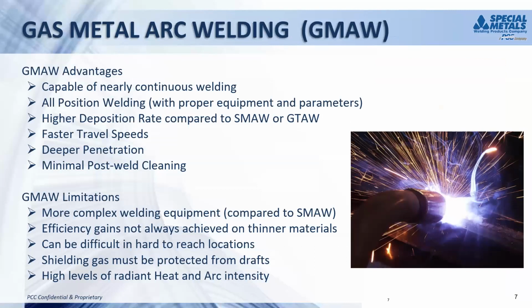All right, now we'll skip over to some gas metal arc welding, or MIG welding. This is probably gaining a lot of steam in the last few years with the nickel alloys because you can do much more continuous welding. We're now starting to put wire in drums, so you can do, not thousands of pounds, but at least 200 to 500 pounds without having to change a spool of continuous welding. Obviously that gives you faster travel speeds and much higher deposition rates, so you can put more metal down. Even with the proper equipment, you can still go all position. We're talking something like a pulsing type power source. You can run the solid wire vertical up or overhead.